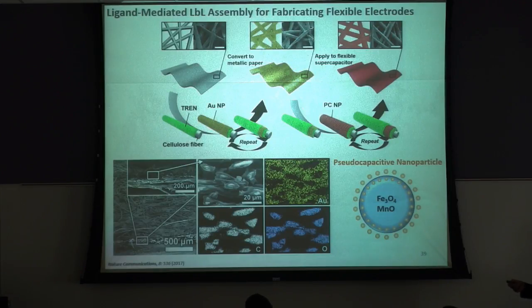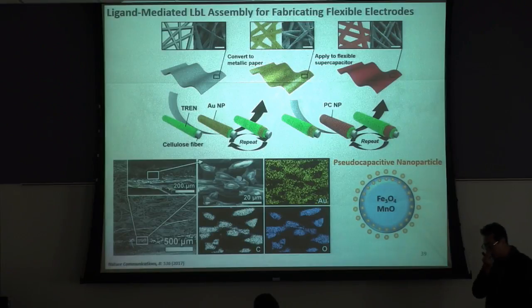So using the ligand-mediated layer by layer self-assembly process, by repeating the TREN and gold nanoparticle adsorption process. After converting the paper to metallic paper, we further incorporate some pseudo-capacitive nanoparticles such as iron oxide and manganese oxide nanoparticles, which have high energy density. So this is the cross-sectional SEM image.